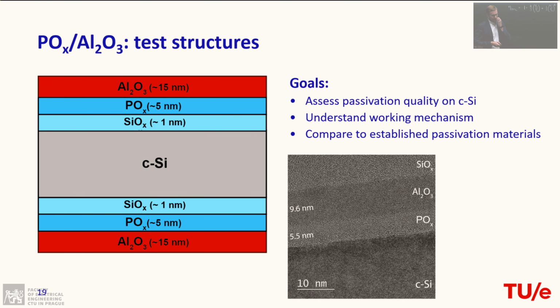And then we look at test structures. Typically for passivation studies, people like to look at symmetric cases. So you have your crystalline silicon wafer, then your passivating stack on both sides, and you try to understand how well this is passivating. The working mechanism, of course, is interesting, and you want to compare it to other kinds of passivation materials. You see here already a picture from the microscope where we indeed managed to make these layers as closed layers, even with very low thicknesses. So everything is nice and conformal on your crystalline silicon surface.